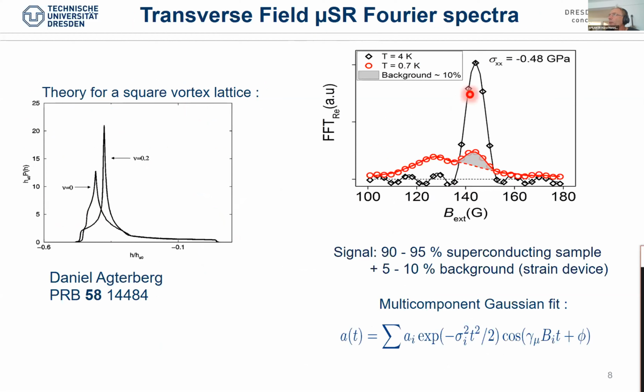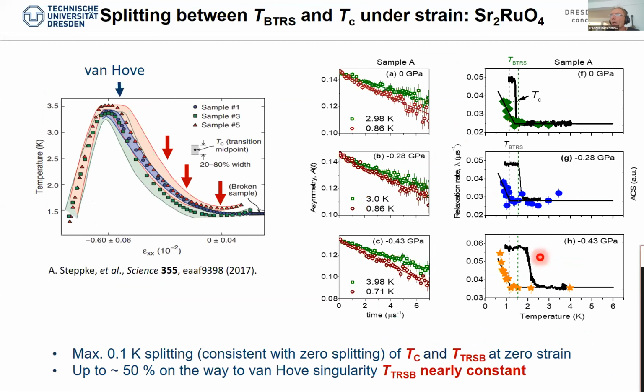Above TC, that is the black curve, we have seen the internal field, which is basically the same as the external field. But then below TC, you see this broad distribution here, which tells us in an analysis that we get really 90 to 95% of the signal from our sample and only 5 to 10% from the background of our sample holder. So now we can go to zero field μSR and look for the time reversal symmetry breaking.